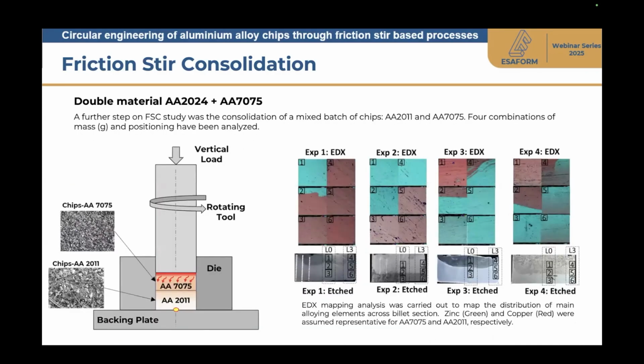It should be observed that with the criterion number 5, as I told you, the best one, more or less in the evolution of the process, we are able to reproduce the distribution of consolidated, not consolidated in the transverse section of the billet. So this was the most effective criterion in terms of prediction of bonding materials.